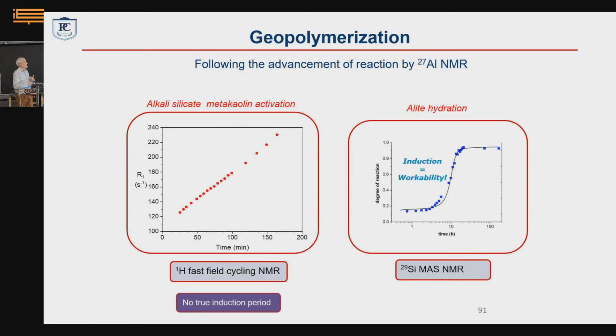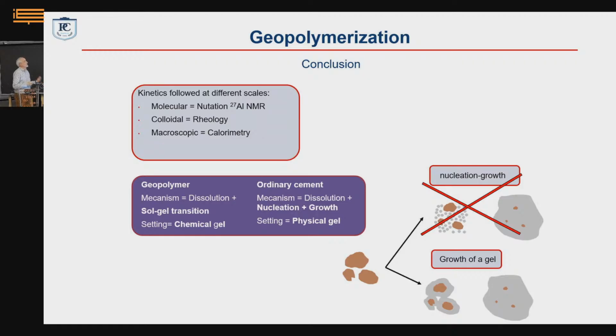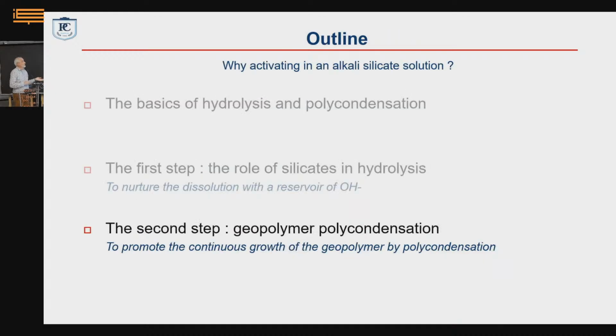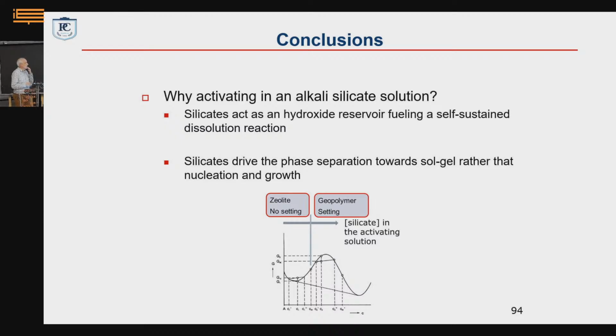So it's very different with the cement paste. No induction period. We have a linear process, which, again, I can discuss with you, but that translates the fact that we are not in a nucleation and growth process. It's normal. We are dealing with an N-A-S-H, with a gel, with something amorphous, so there is nothing to nucleate. And we are dealing with a sol-gel separation. This sol-gel separation occurs because we are dealing with a high concentration of silicate initially. So we are past the inflection point of the free energy curve. And so we go from nucleation and growth, zeolite formation, to spinodal, to make things look smart. We can say spinodal, but basically a sol-gel separation. That is, there is no energy barrier to the phase separation. It proceeds right from the start and in the volume.